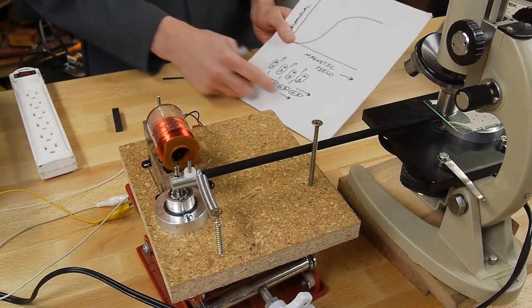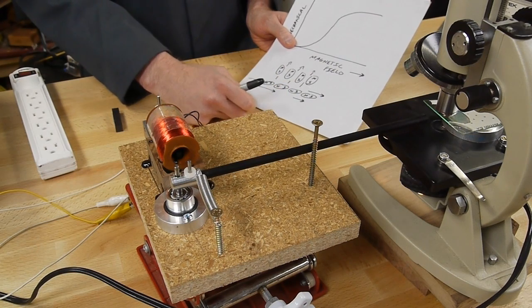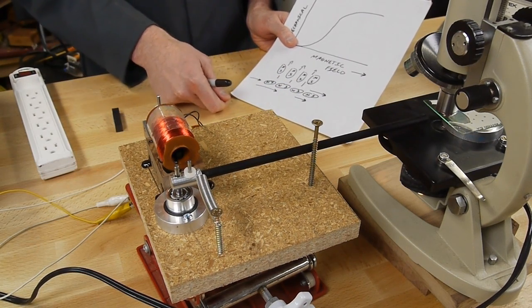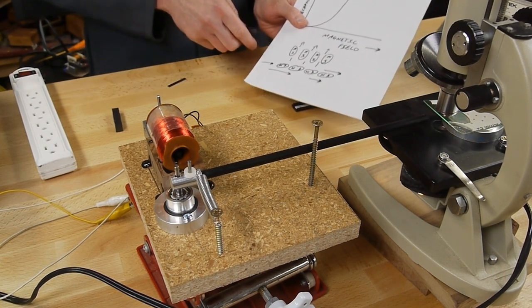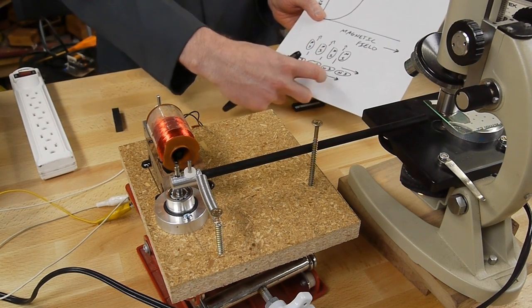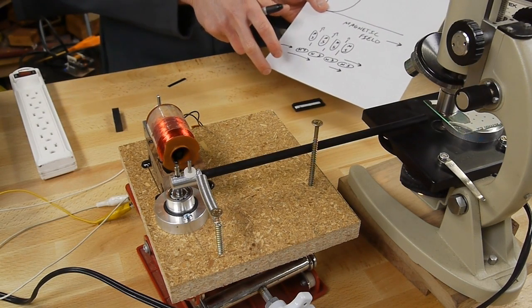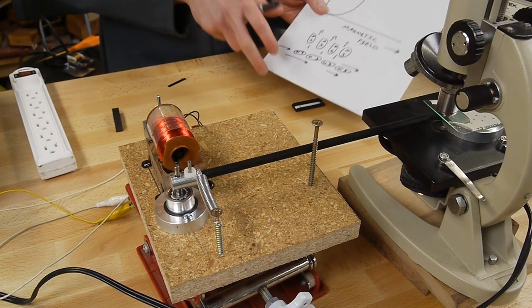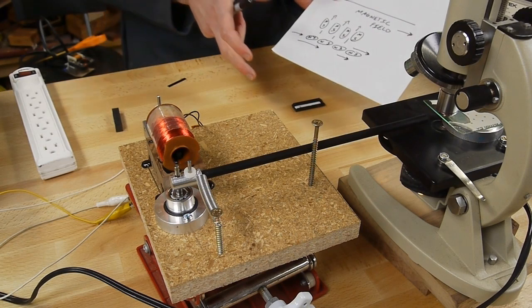Finally, there's actually another effect. This is just showing about the same volume but a different size change because of the magnetic field. This is sort of the classic magnetostriction effect. However, for some materials there's also a very slight volume change. So besides the strip keeping the same volume and becoming longer, just putting it into a magnetic field will cause the volume to decrease a very small amount.